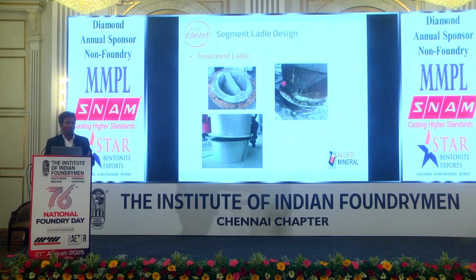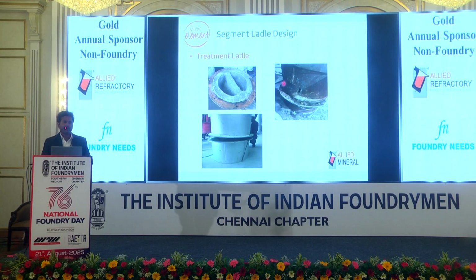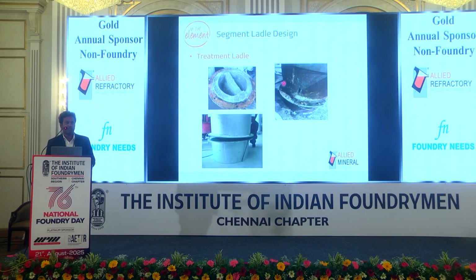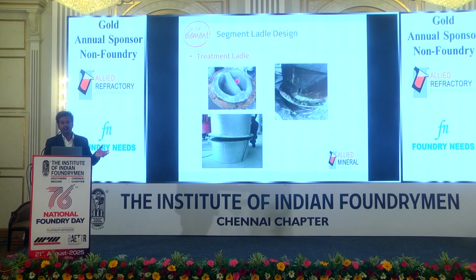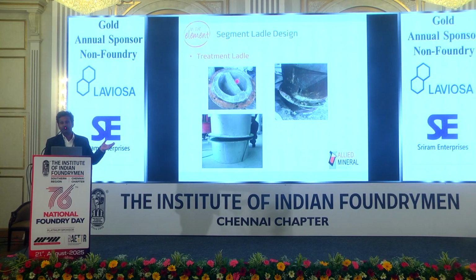So even though the ladle is good, because we are not able to maintain it, the whole complete refractory has to be demolished and relined further. In this way, we can avoid a lot of downtime. We can have a spare pocket area separately, get it ready. As soon as you remove the old one and attach the new one, your ladle is good to go.